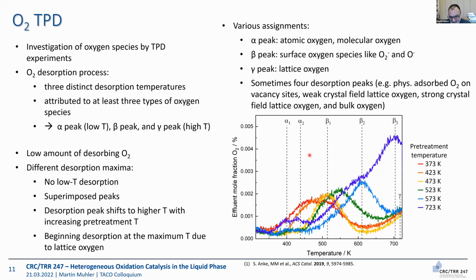Yeah, the next question is now, so there seems to be this more or less labile oxygen that can be converted to water. Can we probe it directly by performing TPD experiments? And when you look at these TPD profiles here, then you see immediately, oh, the quality of the data is not that high. So here we have limitations. When you have a metal, you can perform TPD experiments with very great precision. With an oxide, it's much more complicated.